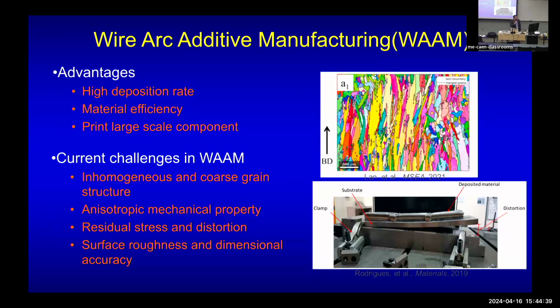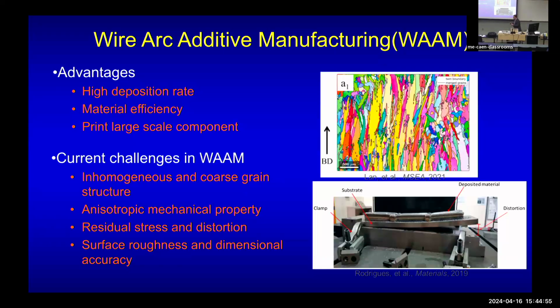So wire arc additive manufacturing, obviously, we know has a high deposition rate, 10 or 20 times faster than powder bed, and the material efficiency is almost 95%. And you can print the largest-scale structures, especially for the automobile and aerospace industries, for large single structures. That's great. But the problem for the traditional WAAM process is the inhomogeneous and coarse grain structure, like without nanoparticles, always like that. Also anisotropic, heterogeneous mechanical properties, distortion, and huge residual stress, and surface roughness and dimensional accuracy are poor.